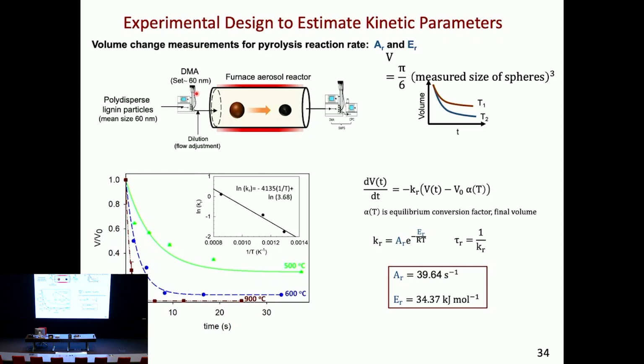So the ability to do very detailed experiments comes to the forte here. Once I have the kinetic parameters, I do a similar experiment now with agglomerates. Now this would be a mobility equivalent size for the agglomerate, and then study if I wait enough time, it's going to become a single sphere, but I can measure the mobility size again.